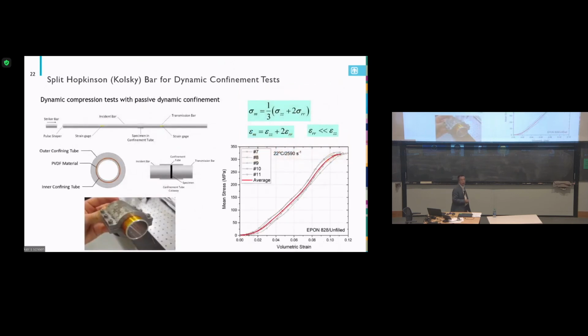Another one is passive. We use a very strong material like steel to confine the sample, so there's no way for the sample to expand laterally. Then we compress the sample, but you need to know how much pressure you apply. It's not constant, not like hydrostatic pressure. That's why we use PVDF, a piezoelectric thin film transducer, to measure the in situ confining pressure during the actual compression. So we have the axial stress, we have the confining stress, we can calculate the mean stress and the volumetric strain, then we have the curve like this. So that's how we run the confinement test with multiple stress states.